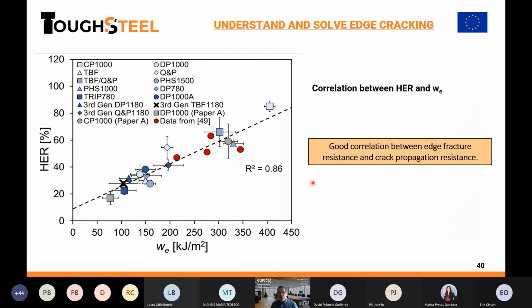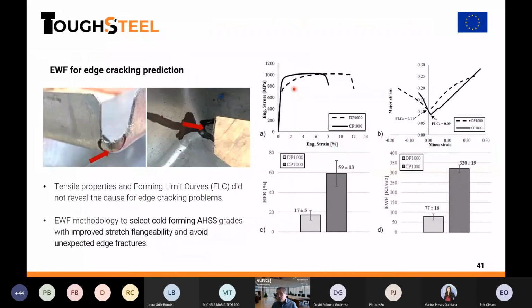Well, let's now focus on edge cracking. This is the plot for many different steels with the hole expansion ratio, a well-known parameter to define stretch flangeability in the industry. We see a nice trend for many different microstructures, third generation, conventional dual phase, many different steels. This is a nice correlation. So the higher the toughness, the higher the hole expansion ratio. So it is supposed to be also useful for edge cracking.